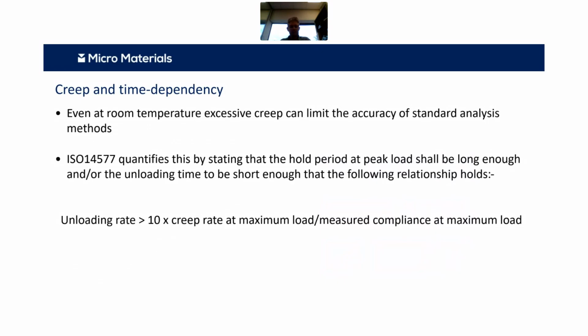that you want to have this relationship where the unloading rate is greater than 10 times the creep rate at peak load divided by 1 over the stiffness. If you do that, then the effect of creep on your unloading elastic modulus measurements is minimized and you can get a reliable value.